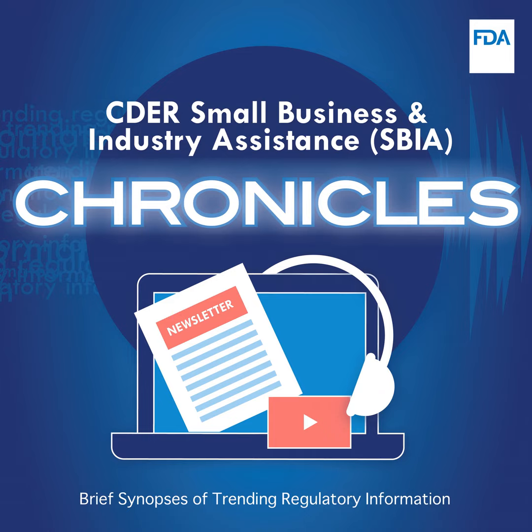A couple more if we have time. One parameter with nanomaterials we think about is the size and the size distribution. This often is a critical quality attribute, or CQA, that will affect the performance of the product. The manufacturing process can directly impact the nanomaterial size. Therefore, process parameters in manufacturing are tightly controlled at the nanoscale to produce the desired size. Differences in the number of atoms may affect the size by several percent at the nanoscale.